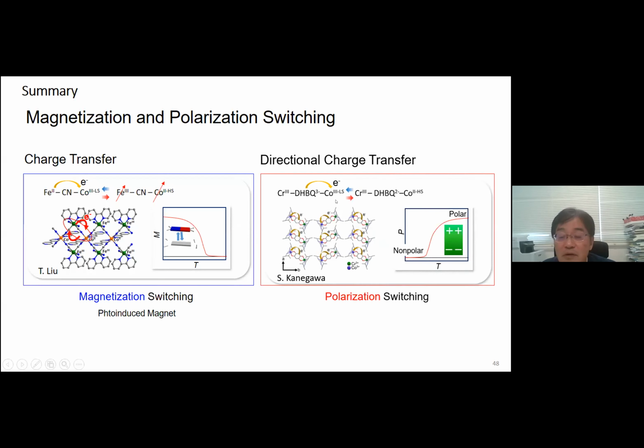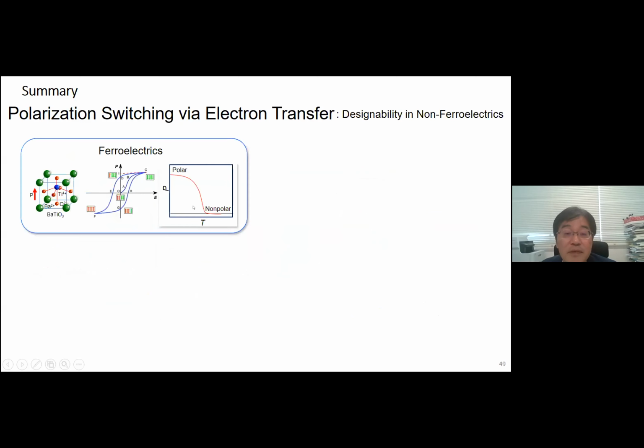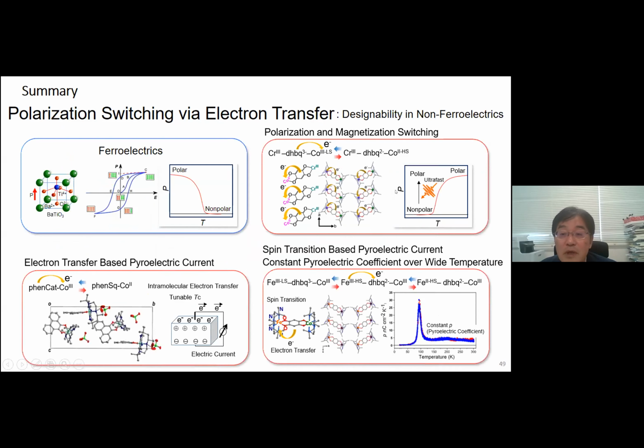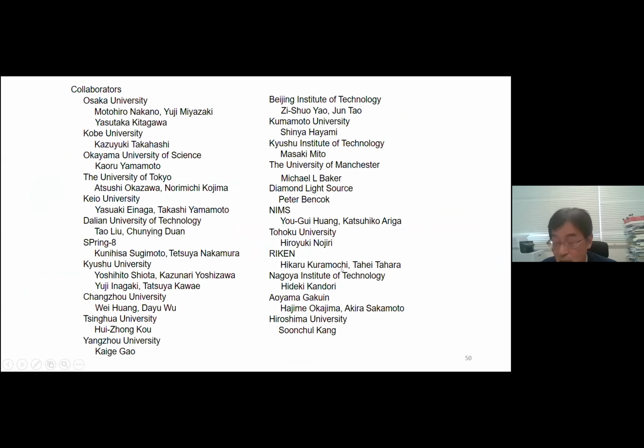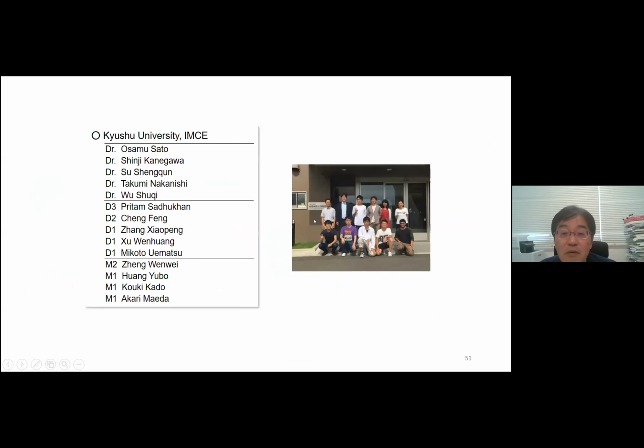material using electron transfer. And it shows polarization switching and magnetization switching. And we observed ultra-fast polarization switching, pyroelectric current, and nearly constant pyroelectric current. And these are our co-workers, and I would like to thank all of them, and this is our group members. Thank you for your attention.